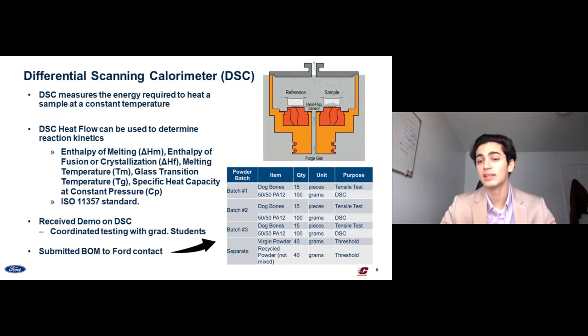So that's everything that we need to determine for Ford if the nylon 12 powder that's being recycled, the 50/50 powder, is some of it thermally damaged. And if it is damaged, is it damaged enough to the point where we can't use the powder again? Or is the quality of the powder still good? And like I said, with the melting temperature point, we'll be able to figure that out.